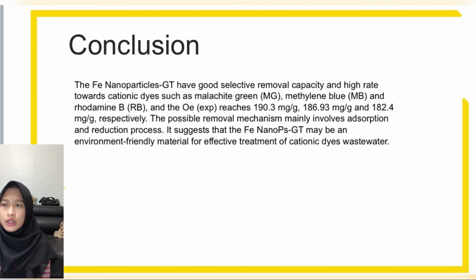190.3 milligram per gram, 186.93 milligram per gram, and 182.4 milligram per gram, respectively. The possible removal mechanism mainly involves adsorption and reduction process. It suggests that the FeNPs-GT may be an environment-friendly material for effective treatment of cationic dyes wastewater.